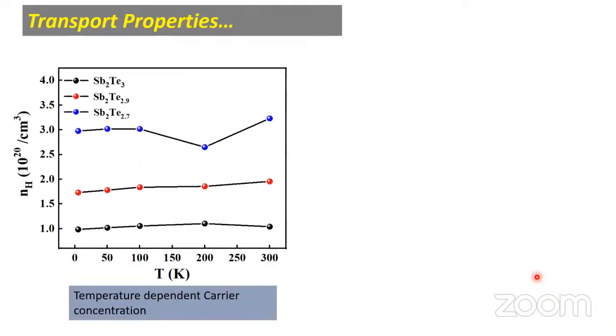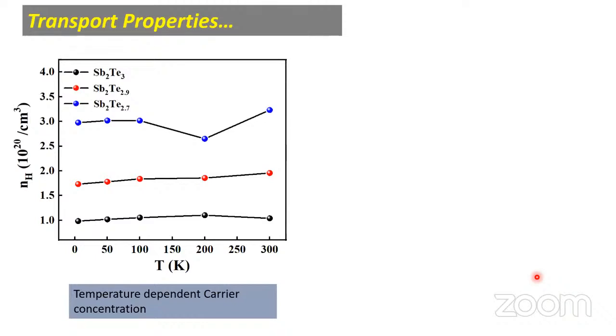So for transport property measurement, at first we have carried out temperature dependent Hall measurement. And from the Hall coefficient data, you can see that all the samples are p-type in nature. And this is desirable, as defects are increasing and the defects each time donate holes in the system, the NH is increasing with incorporation of Te vacancy. But there is no such strong dependency of NH on temperature for all the samples.